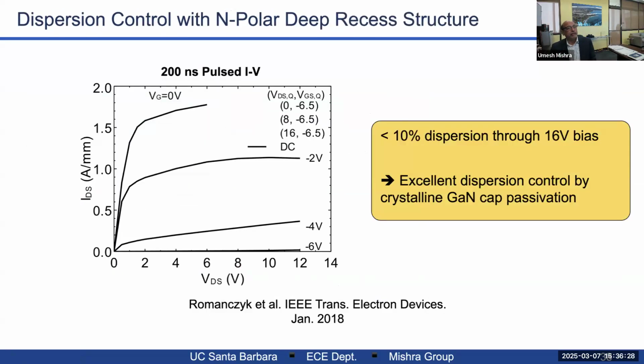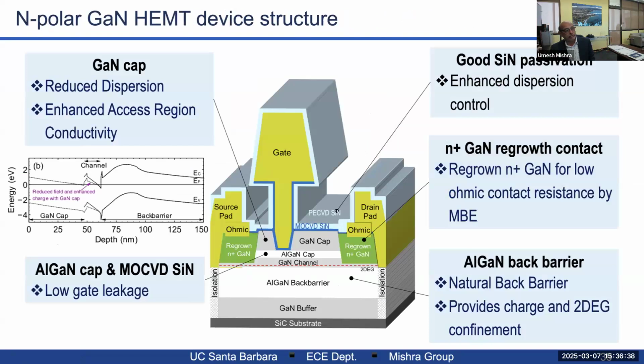So we get terrific dispersion, less than 10% dispersion through 16 volts in the device. Very good current and a very good looking FET. This diagram actually tells you that, in this case, the band diagram showed up well. When I put gallium nitride on the surface, you can see that the electric field in the channel gets reduced, because when I put gallium nitride on the top, it pulls the bands down. So it adds charge here and a little charge on the top.